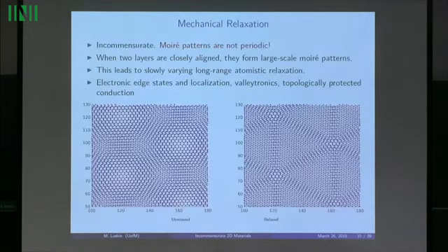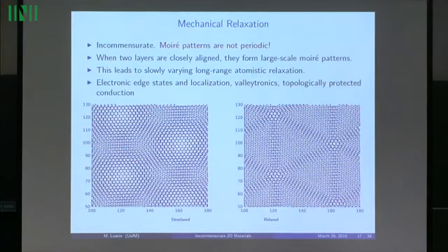So when you move through here, from here to here, or any period, across the unit cell, then you're crossing the disregistry of gamma 1 and gamma 2 one time. So moving through the Moire cell once in real space is moving through the unit cell of the other layer once.